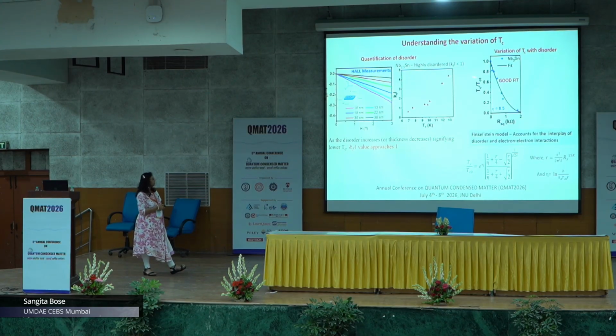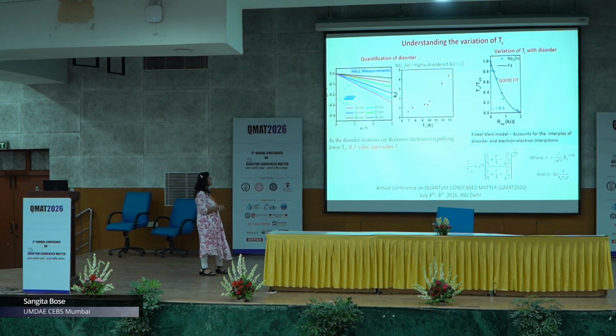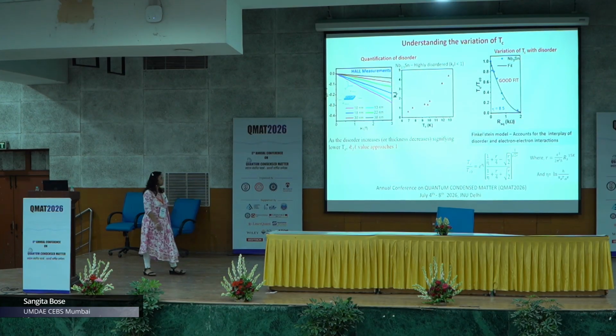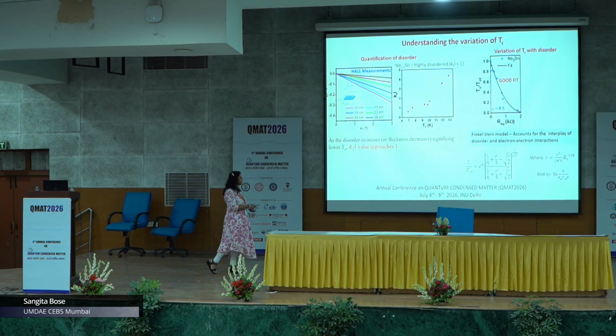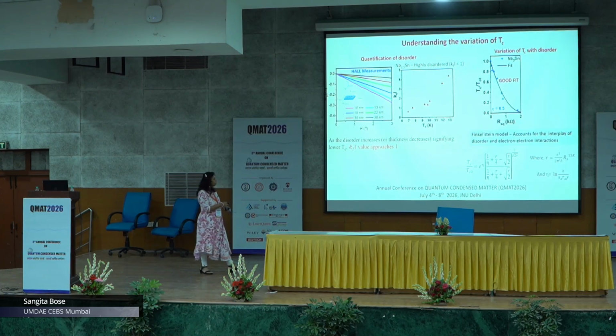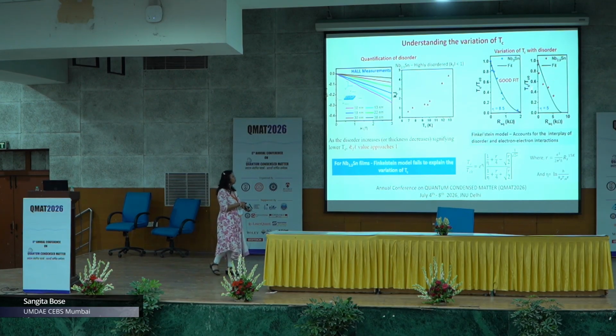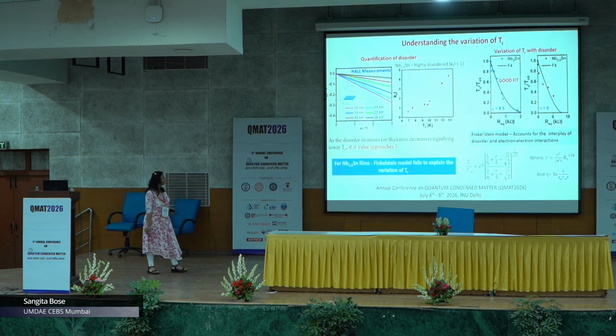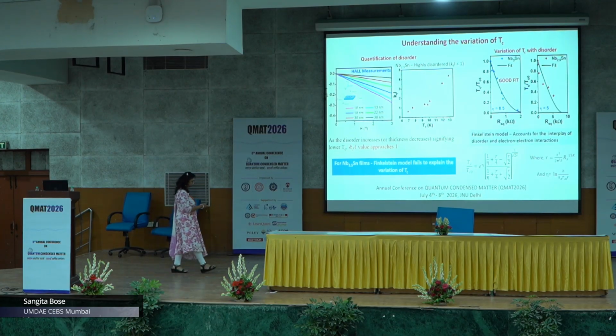So, if you want to understand the variation of Tc with the thickness, what we do is plot the variation of Tc with the square resistance, basically understanding whether the disorder is having any role to play in the variation of Tc. Yes, it does, because if we just use the Finkelstein model, which accounts for the interplay of disorder and electron-electron interactions, we see a very good fit of our data with the Finkelstein model for these stoichiometric systems. But if we look at the off stoichiometric system, we actually don't see any fit at all. So, this is no fit. So, we say that in these off stoichiometric systems, the Finkelstein model fails to explain the variation of Tc.